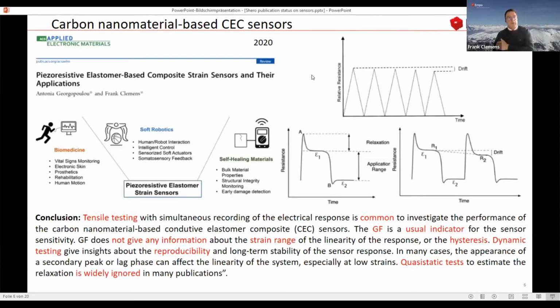So how did we look inside these materials when we worked in the Shero and in the SMART consortium? Here you see, for example, a paper which was published at the beginning of the Shero project, where we started to look a little bit closer inside piezoresistive sensors based on carbon materials. And here you can see typically what people are looking for. Either people are using this kind of cycling testing, as shown in the presentation before. And this is pretty good to show the reliability of the sensor, and also to investigate the so-called gauge factor, which gives you more or less the sensitivity of your sensor.